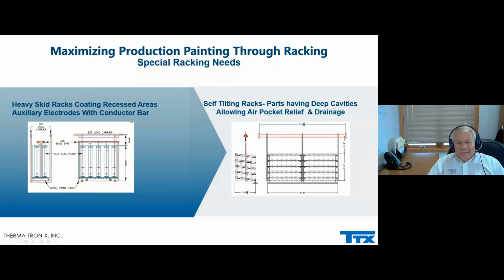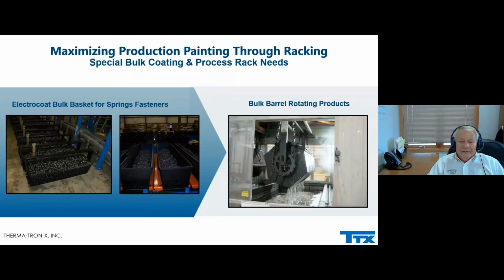You end up having the ability to get uniform coating. They're self-tilting racks, for parts that have deep cavities allowing air pockets. These are sail racks if they go into immersion or even immersion chemicals. There are numerous ways of tilting these racks, and the flexibility can be done through using cone shapes and sail, what we call sail flags, that allow the rack to burp those loads as it's going through an immersion process.